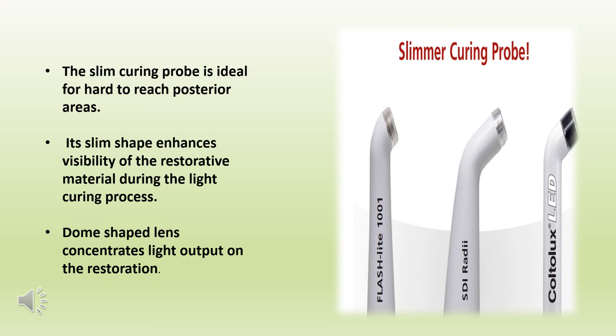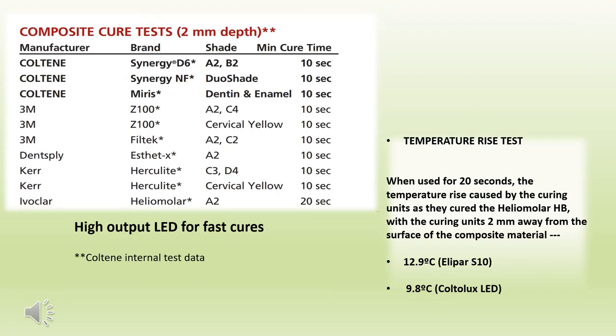The slim curing probe is ideal for hard-to-reach posterior areas. Its slim shape enhances visibility of the restorative material during the light curing process. The dome-shaped lens concentrates light output on the restoration. Because of high output LED, fast curing can be achieved. Coltolux can cure 2 mm composite resin in just 10 seconds. Also, the temperature rise is lesser as compared to the other LED curing units. Thus, the practitioner has the greatest freedom to cope with the diverse demands of modern clinical practice.